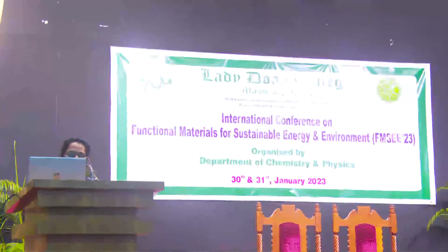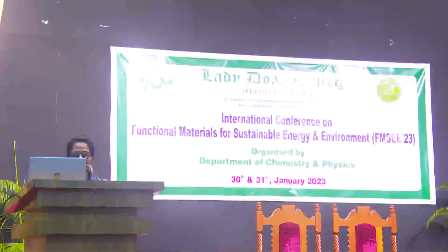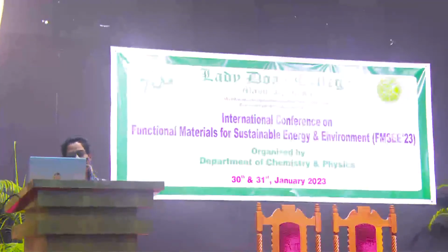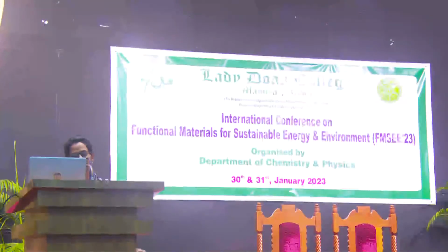In XPS analysis, I have observed the oxidation state of all the elements present in the sample. Copper is found to be copper plus, barium is barium 2 plus, tin is tin 4 plus, and sulfur is found to be S 2 minus, which agrees well with the stoichiometric molecular formula of the material CBTS.